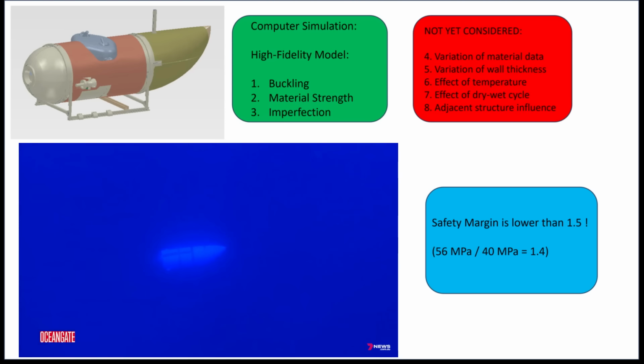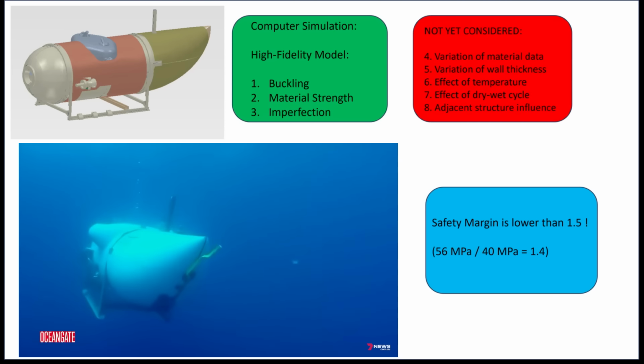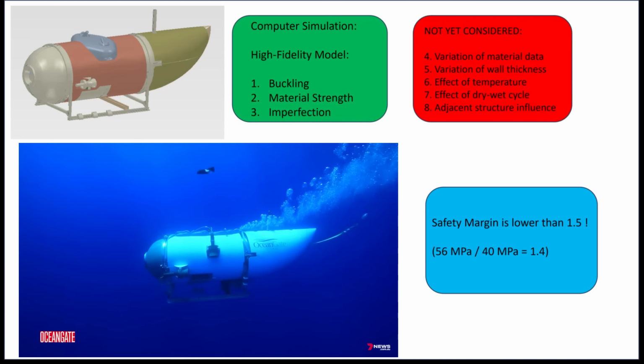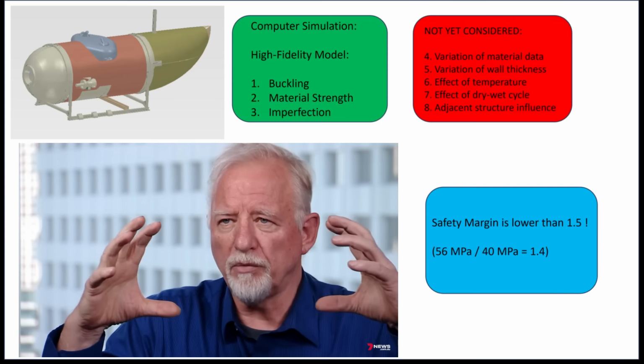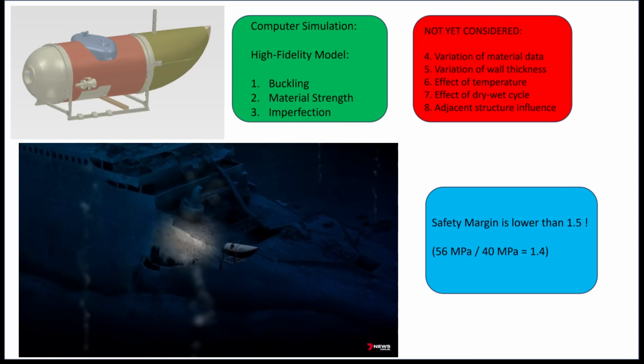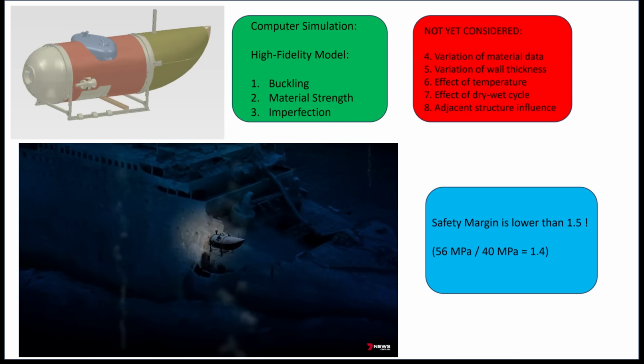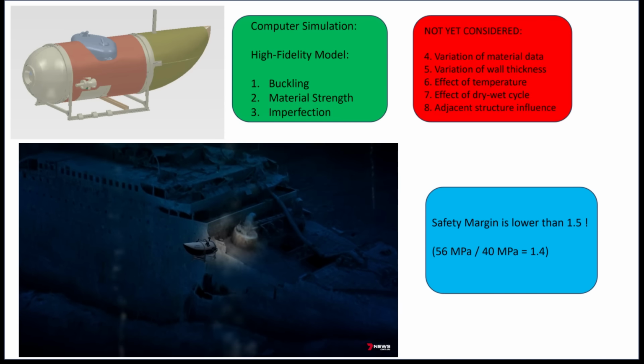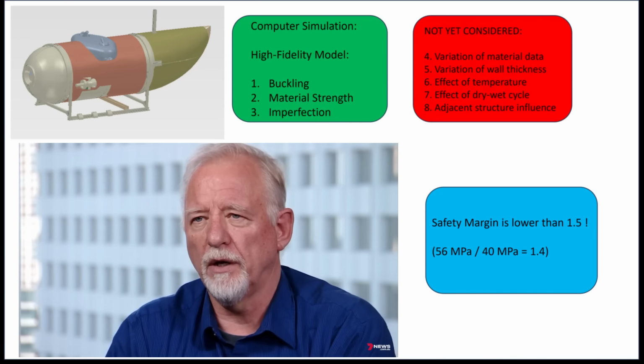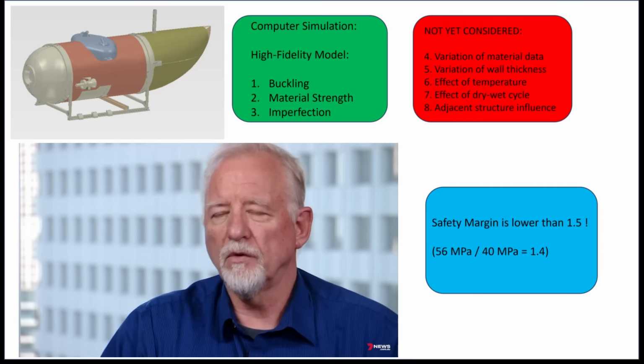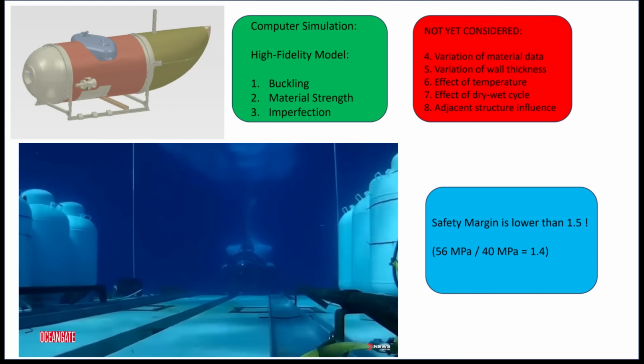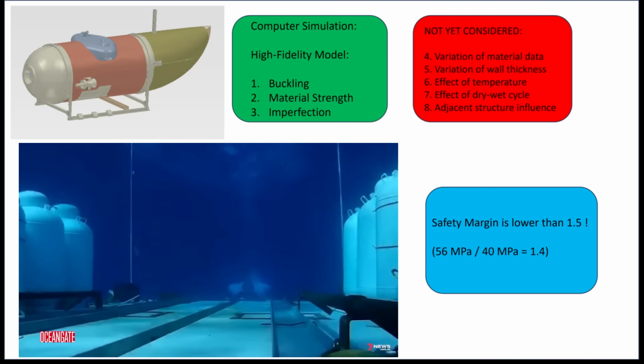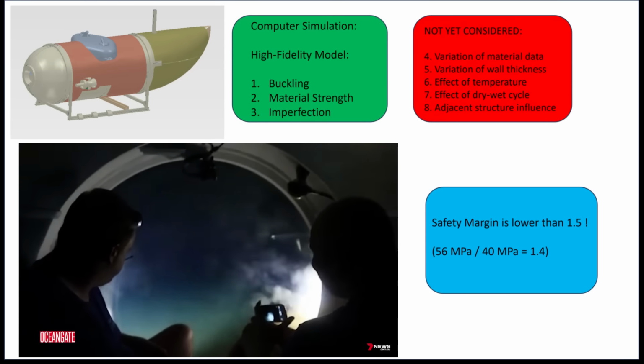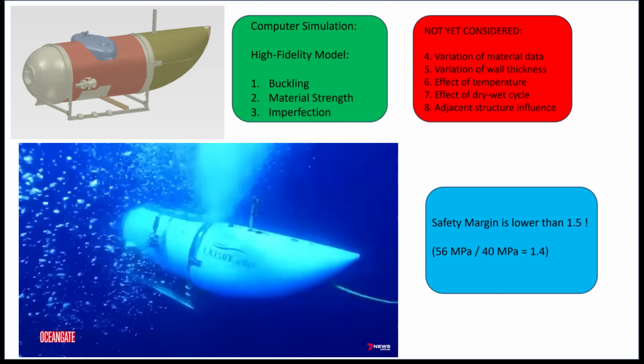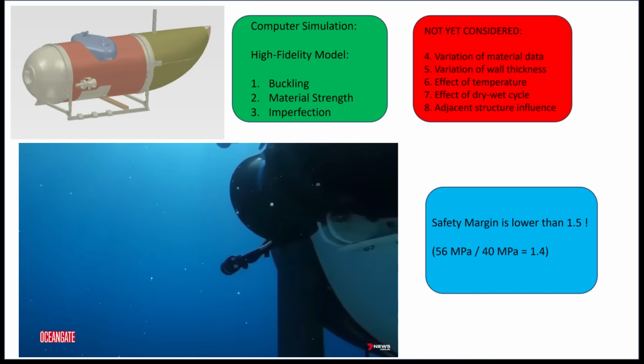The second one is you've got to put it under constant pressure for 3 months at 6 times the pressure, because plastic, you've seen it, it creeps. It just keeps moving. So it's like, well, it might be good for the first hour, but after 4 hours, all of a sudden it deforms and it collapses. So you've got to put it for 3 months under 6 times the design pressure. And after that, you've got to cycle it at full pressure for 1,000 times. Well, that takes the better part of 2 years to do.